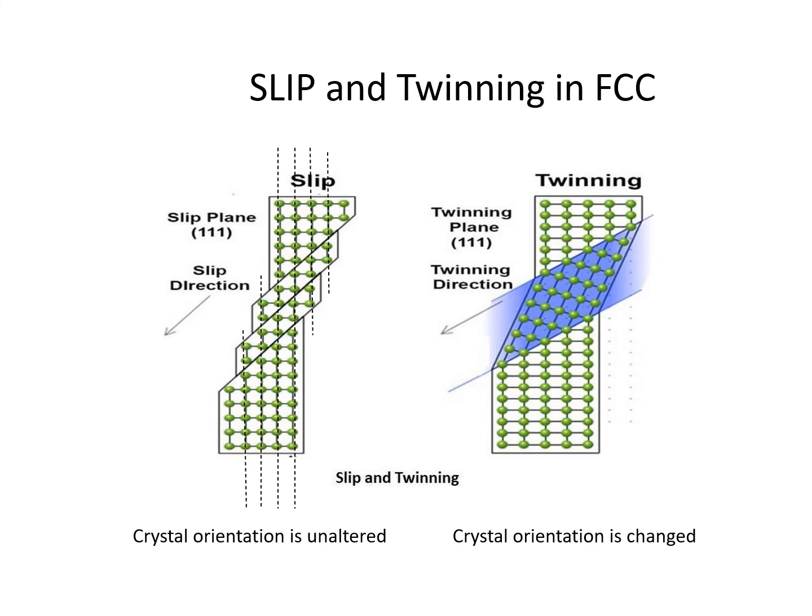The other way to create shear deformation is through twinning. Twinning is far more prevalent, I think, than people appreciate. And what we have here is an illustration of what goes on when you're twinning. This is a tensile specimen. So if you have a tensile specimen and you have a slip plane here, and you break all the bonds of the dislocations along this plane, you can shift parts of the crystal with respect to the other.